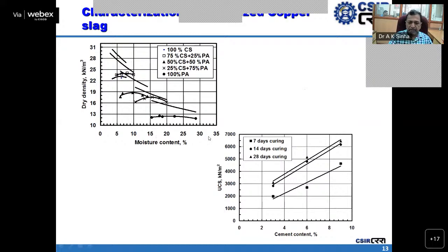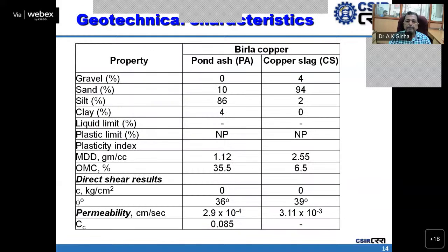25%, 50%, 75%, and it was found that after blending with pond ash, density is reducing a little bit with the addition of pond ash. Copper slag was also blended chemically with cement in different proportions, 3 to 9%, and it was found that UCS value is increasing with respect to curing periods, and with respect to cement content also. So these are some of the properties of pond ash and copper slag collected from the Birla Copper Industries.